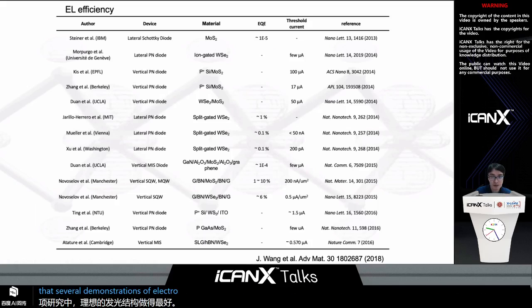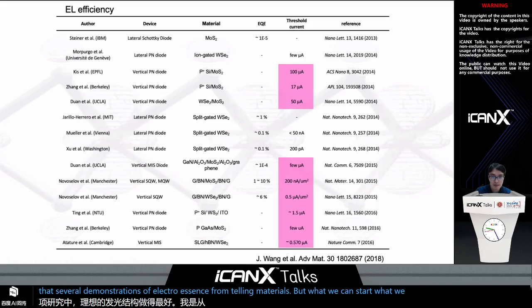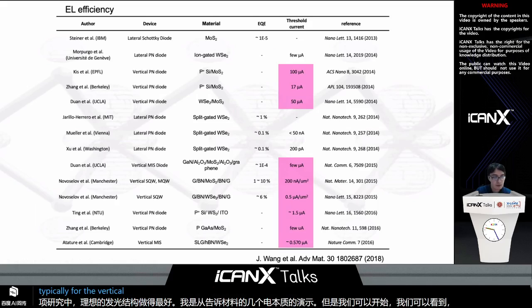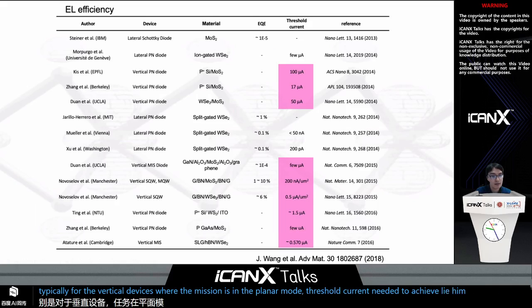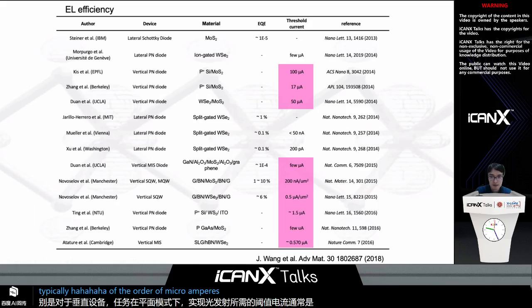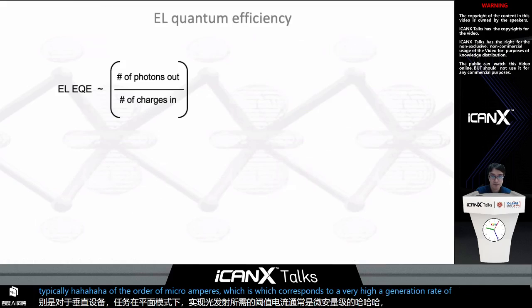electroluminescence from 2D materials. But what we can see is that in most cases, typically for the vertical devices where the emission is in the planar mode, the threshold current needed to achieve light emission is typically of the order of microamperes, which corresponds to a very high generation rate of electron hole pairs.